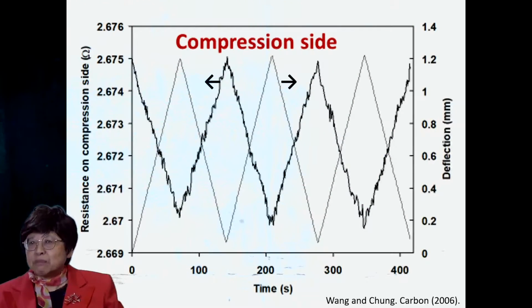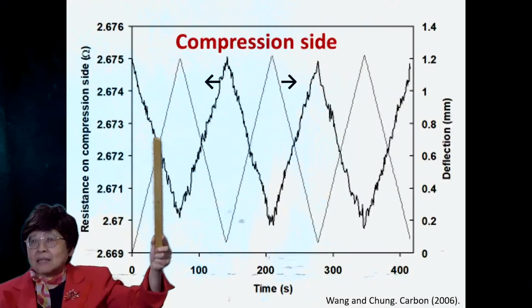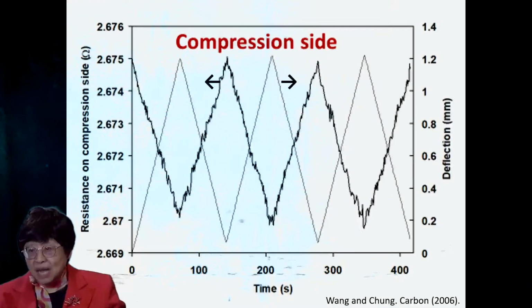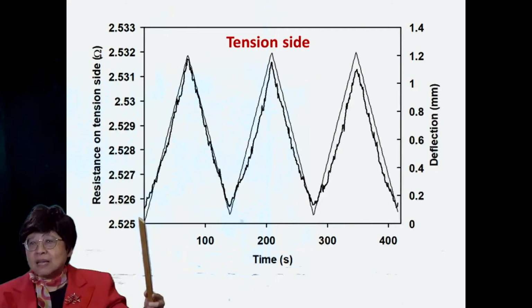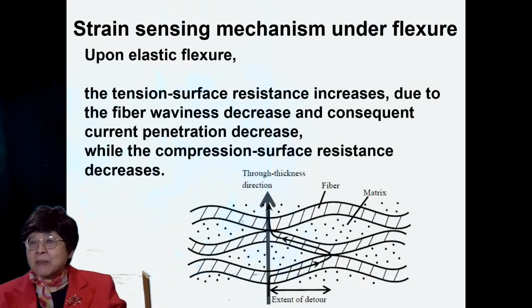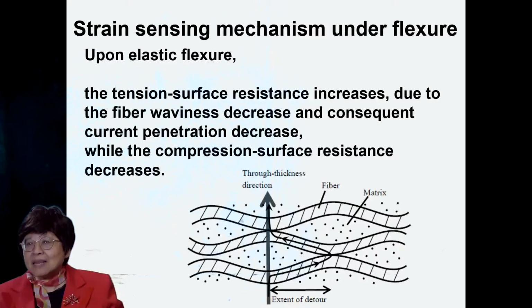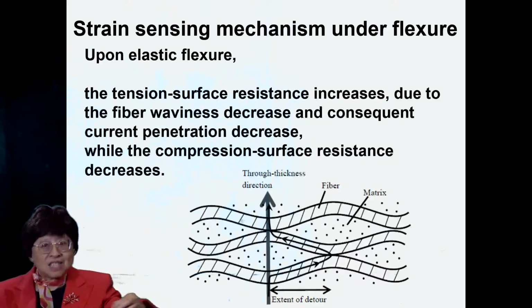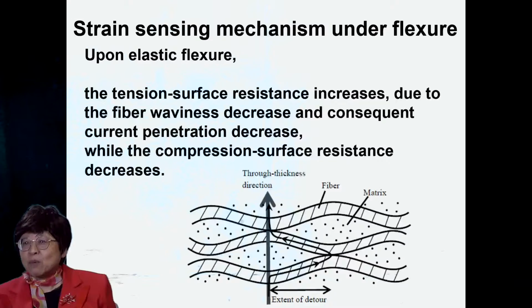And this shows the compression surface resistance in bold line. Now, every time one flexes, that compressive surface resistance goes down, and the opposite for the tension side surface resistance. And the reason is this: upon elastic flexure, the tension surface resistance increases due to the fiber waviness decrease, because you are stretching horizontally, so the fiber waviness decreases, and thus the current penetration decreases. And under compression, it's just the opposite.